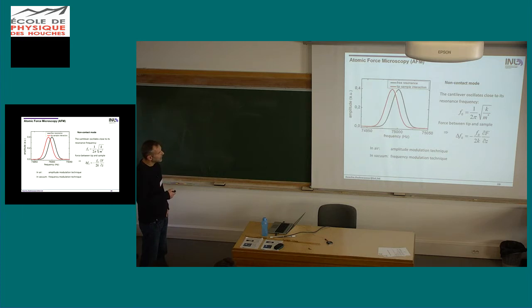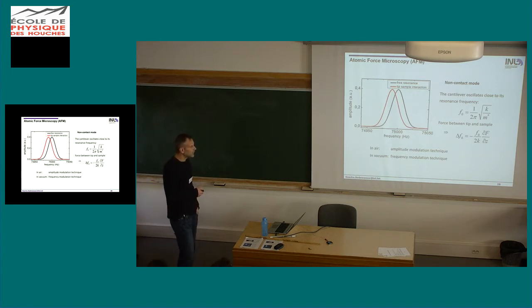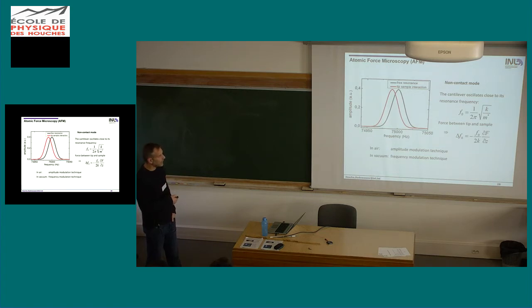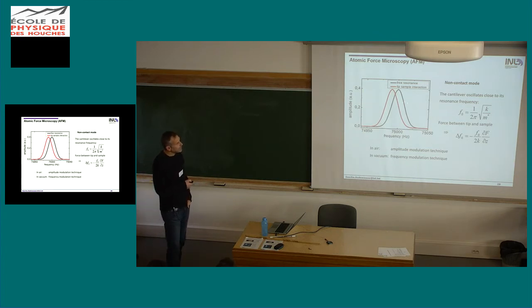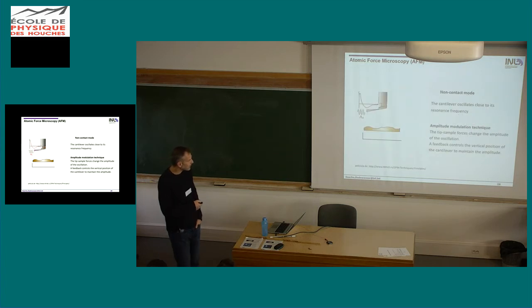mode does is you excite, let's say, to one side of the resonance curve, and then as soon as your resonance curve shifts, your amplitude would go down if you excite there. So what you do then is you move closer until you recuperate your amplitude. This is why it's called amplitude modulation. However, if this curve gets very sharp, because there is no damping due to air in vacuum, then it is very narrow, and you will move very quickly out of the resonance. So if there's only a slight shift, you might actually fall to zero amplitude. And that makes it very complicated to control. So in vacuum, people use the frequency modulation technique, which I will also explain in a moment.